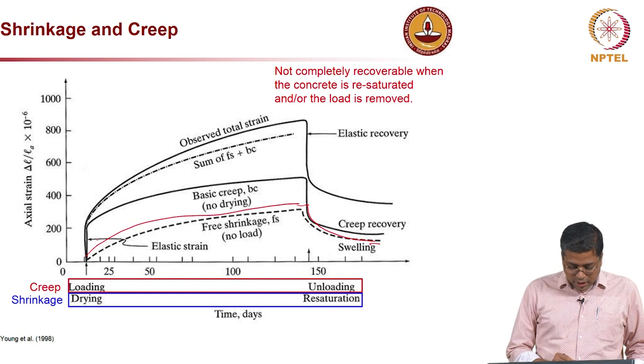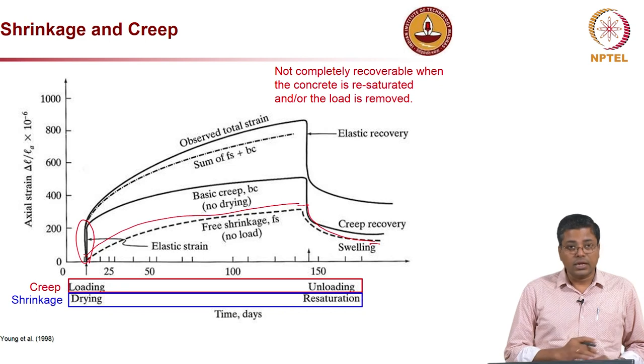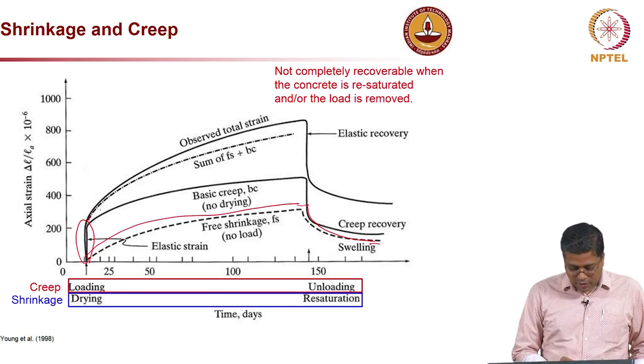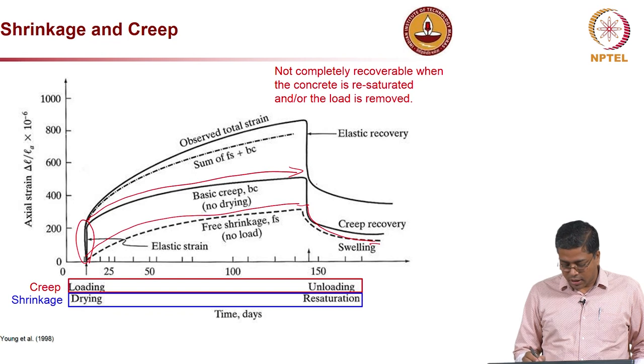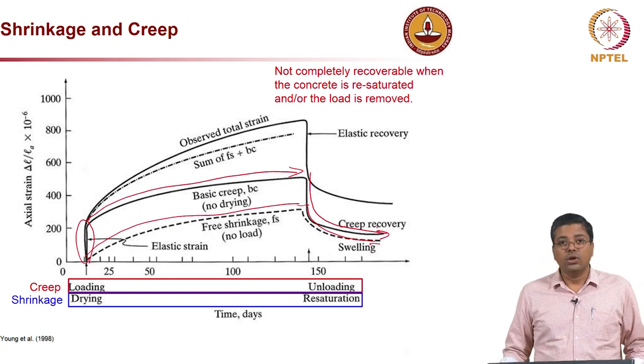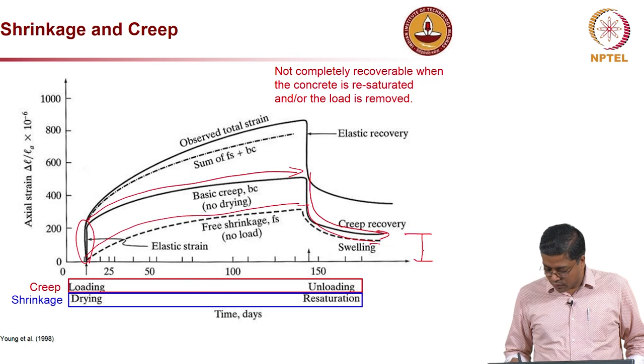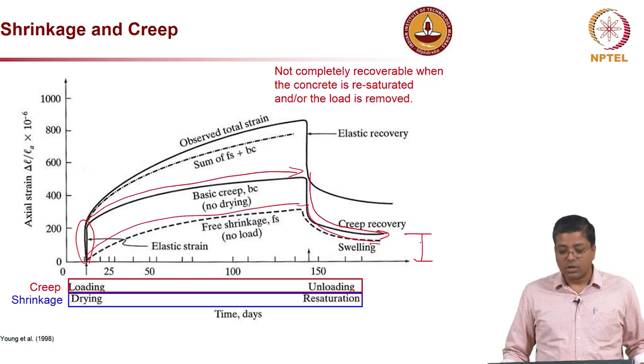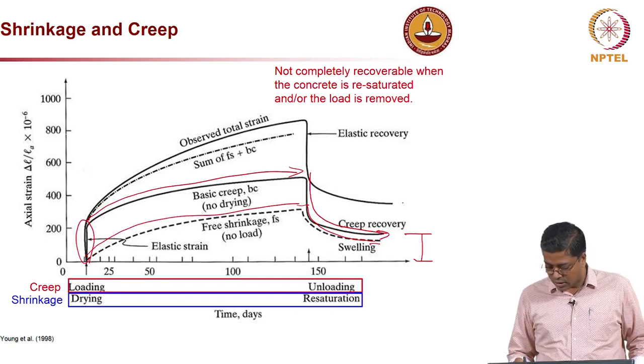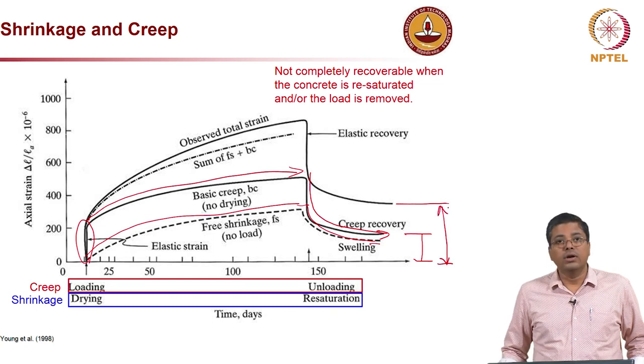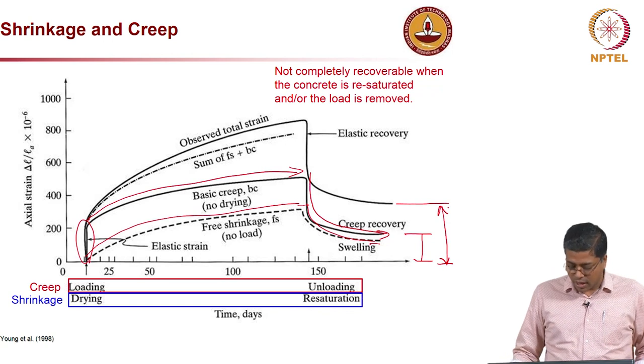Okay. And in the case of creep, in the beginning, as soon as the load is applied, there is an elastic strain, and then after that you have this creep strain. At this point the unloading starts, and you recover some of the creep strain, but not fully. So you have something which is not yet recovered. Now if you look at the sum of these two, you can see in this graph that this much strain is not recovered even after resaturation or unloading.